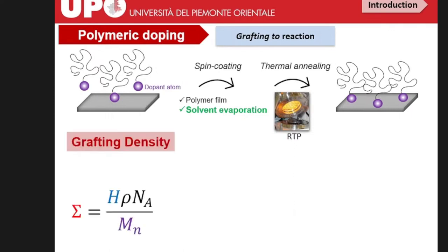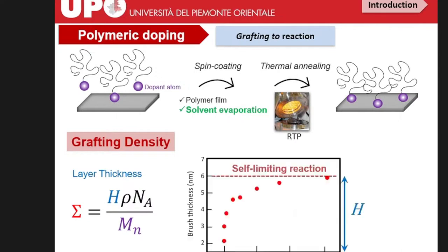The grafting density, that means the amount of the polymer that is grafted on the surface, is described by this equation that mainly depends on 2 variables. The first one is the layer thickness. This reaction, the grafting to reaction, as I mentioned before, forms a monolayer. It means that if we follow the kinetics of the reaction, we observe that it will reach a plateau, because this is a self-limiting reaction.